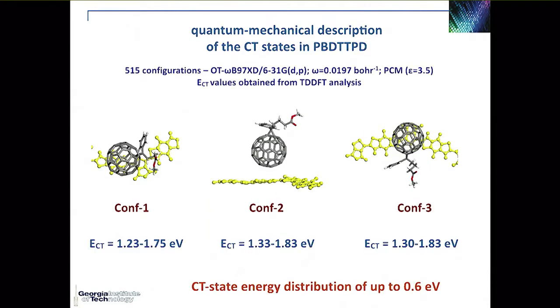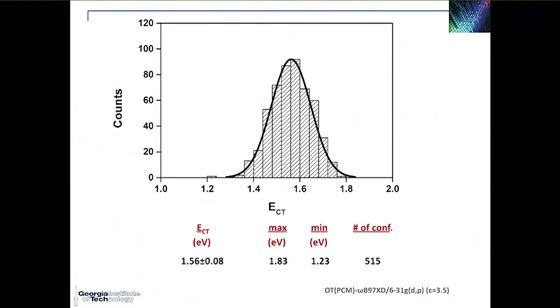But then, indeed, you have also those fullerenes coming in very different configurations along the chains, and you can easily expect that if you have different configurations of the fullerenes on top of the donor or the acceptor, you'll have differences in the electronic couplings between the chain and the fullerene, and that will lead to a significant distribution in the energy of the charge transfer states. And actually we get CT state energies that evolve between 1.2 eV and 1.8 eV, so over 0.6 eV in that case. And you can nicely fit the distribution into a Gaussian.